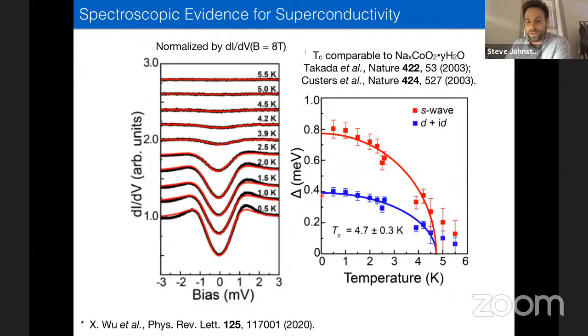Here what we find is that if we do this with a D wave or an S wave, we just differ in what the magnitude of the gap is. That comes from the fact that the D wave has a 2 in the prefactor. So what you call delta changes, but the temperature trace basically predicts a TC of about 4.7 Kelvin with some indication of a gap at higher temperatures, but with very large error bars.